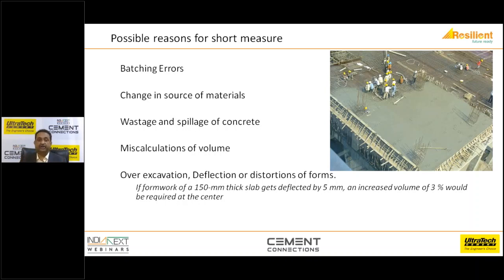The change in source of materials. Suddenly you have taken material which is not in the approved material list, and then you have got a higher specific gravity or a lower specific gravity. You have a problem because you normally batch in weights and sell in volume. So specific gravity is a key component in determining your measure. It could be wastage or spillage at site, but most commonly what is being observed is that it could be a simple case of miscalculation of the volume.